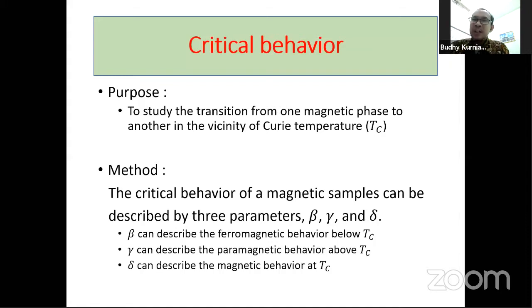For the magnetocaloric effect, we want to study the transition from one magnetic phase to another in the vicinity of the Curie temperature. That's why in our experimental measurement, we focus on several temperatures for the magnetization process. From this, we can explore the three parameters: beta, gamma, and delta. Beta means the ferromagnetic behavior below TC, gamma the paramagnetic behavior above TC, and delta the magnetic behavior at TC. Those are the three parameters that we want to deliver in this presentation.